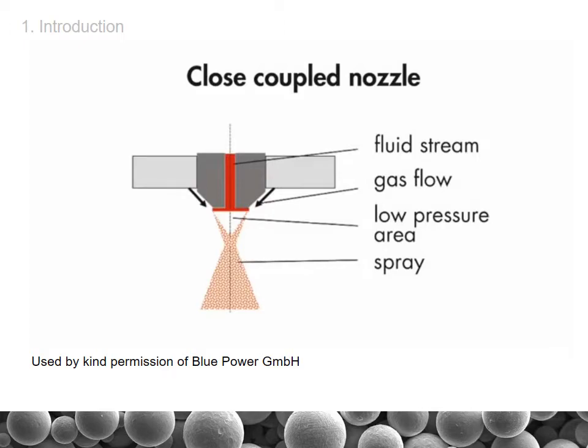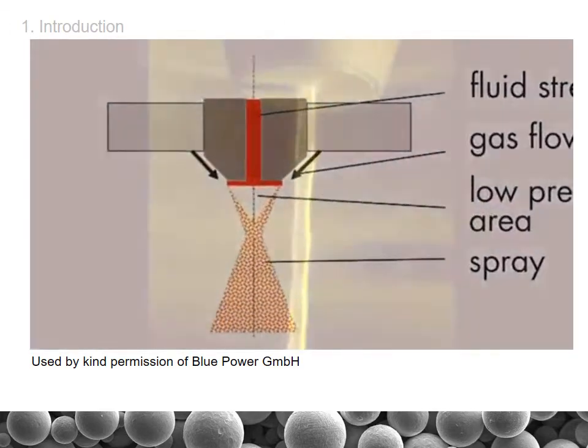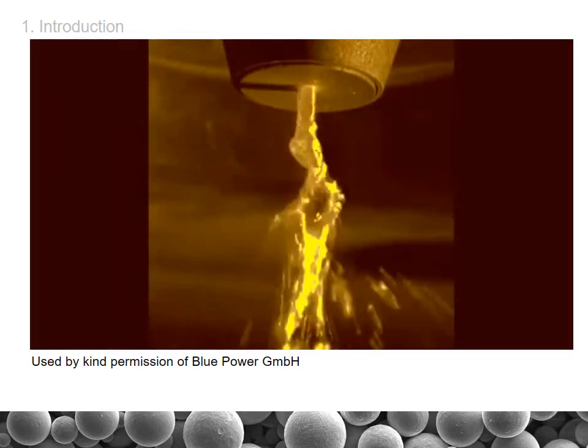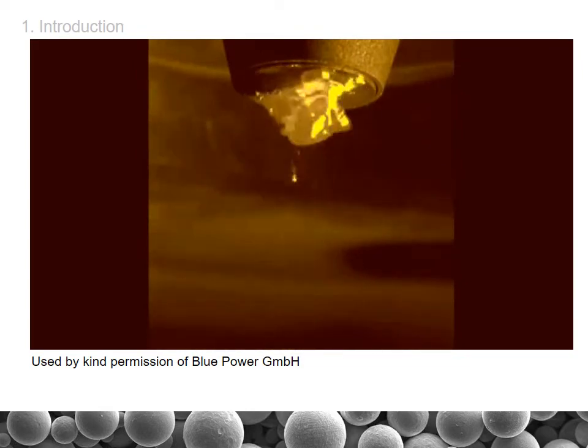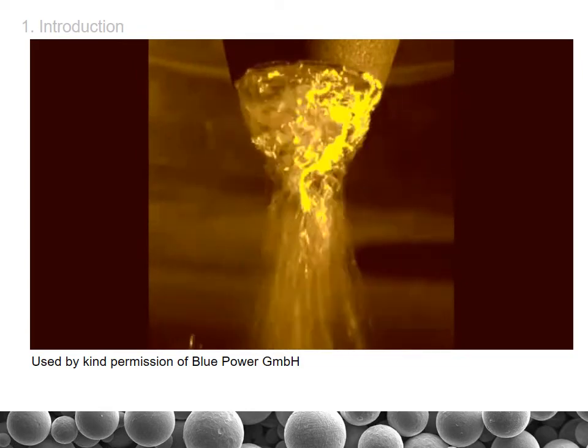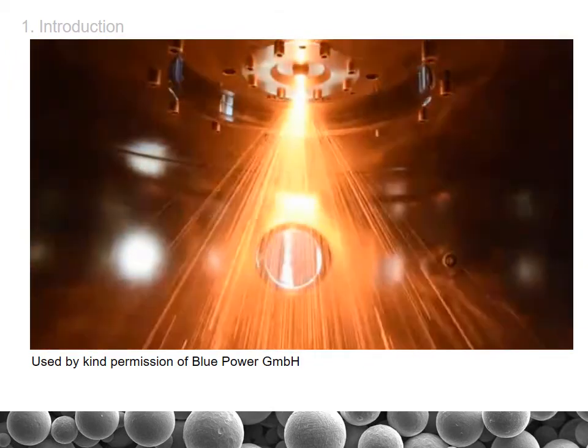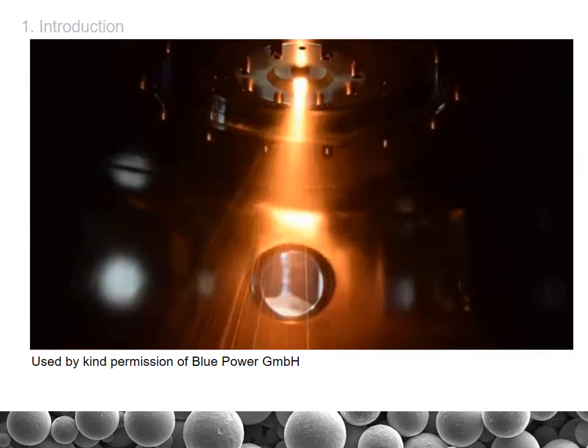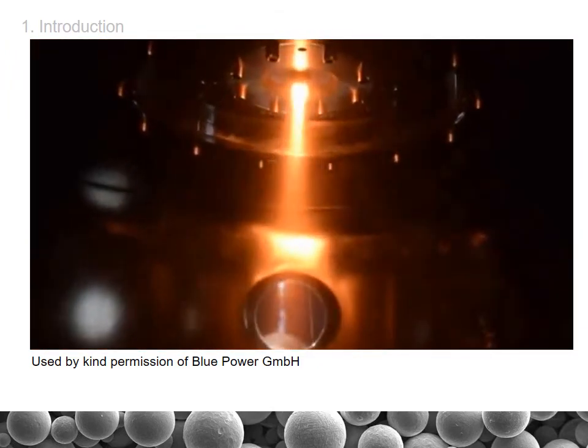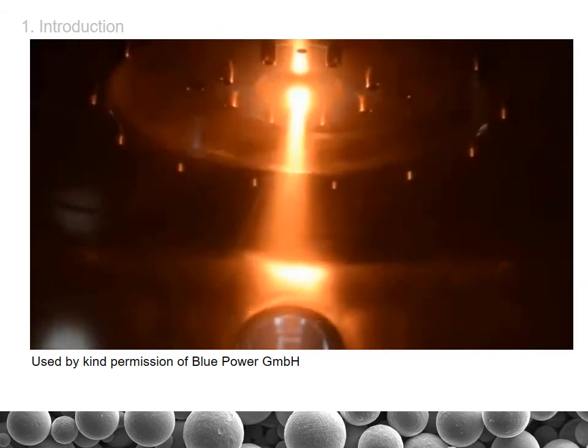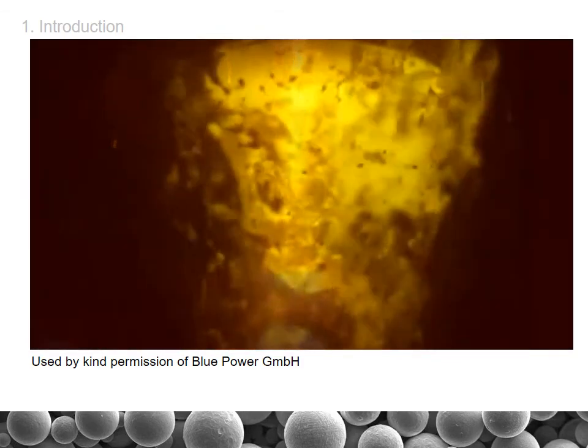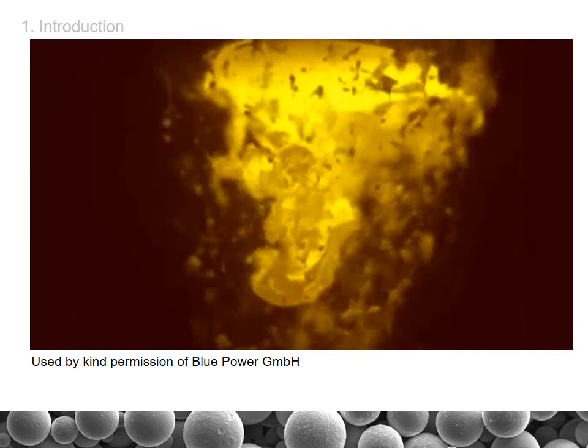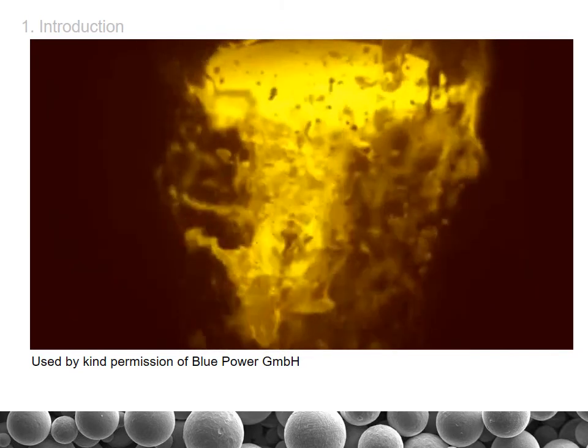When I talk about metal powder production, I talk about gas atomization. You can see here a typical close coupled nozzle or pre-filming nozzle. The melt comes through the melt delivery tube here. It comes to the edge of this nozzle face where it builds some kind of melt sheet, which is atomized here by the circumferential gas flow.